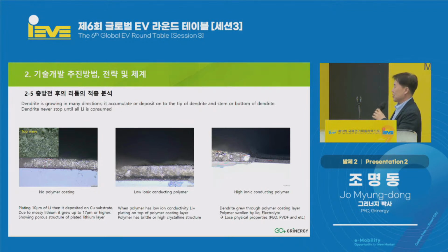structure-wise, of course, the dendrite grew through the polymer coating layer, polymer swollen by liquid electrolyte. And polymer has brittle or high crystalline structure. And we have done the copper foil coating, and lithium ion goes down here, and it penetrated through polymer, and then once again, what I have shown you, the polymer can be used to suppress the formation of dendrite.